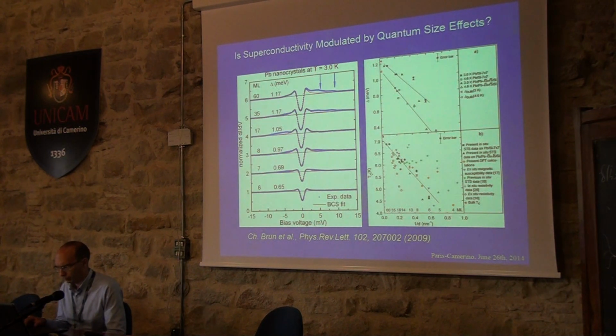However, it was not shown that there is any enhancement of superconductivity, but rather, with reduced thickness, you reduce the superconducting gap, as in this paper by Brun et al. published years ago. You see on the top part of the left diagram, you have a large superconducting gap, but when you reduce the thickness of the islands, you get a smaller and smaller gap, and finally a very reduced gap at 6 monolayers.